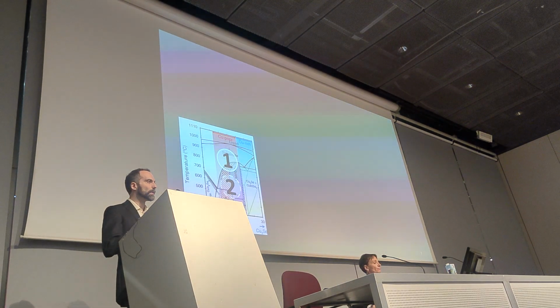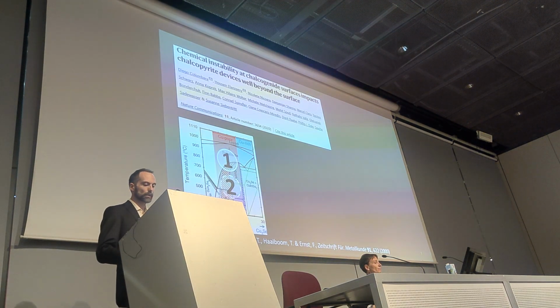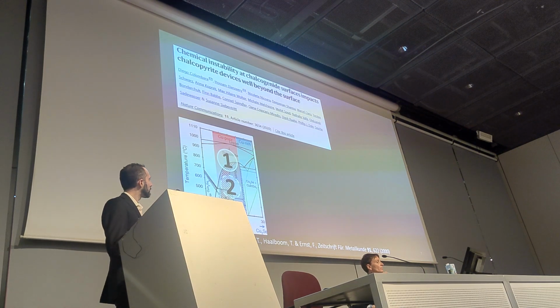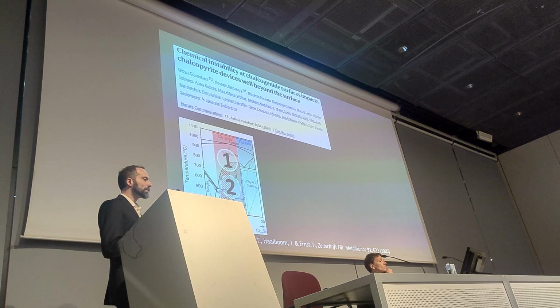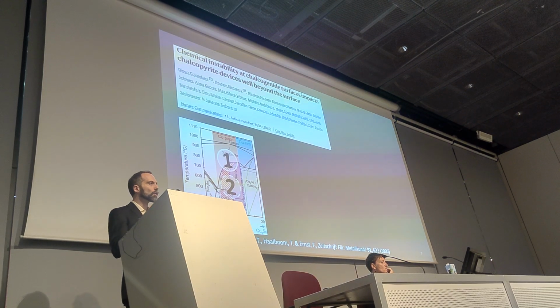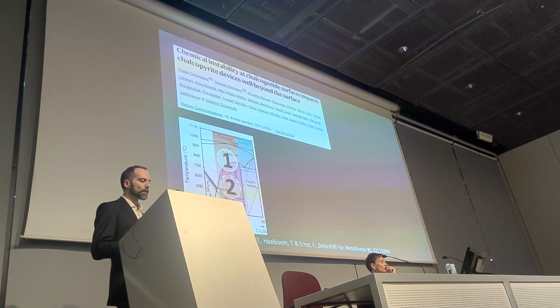So if we learn how to make the material better, we can aim to get there. But first, we should look into the ternary system, and now I'm going to show you the pseudo-binary indium selenide copper selenide section, but the same also holds for the gallium selenide copper selenide section. And you see there is a quite wide homogeneity region on the copper poor side, whereas on the copper rich side we are limited by stoichiometry.